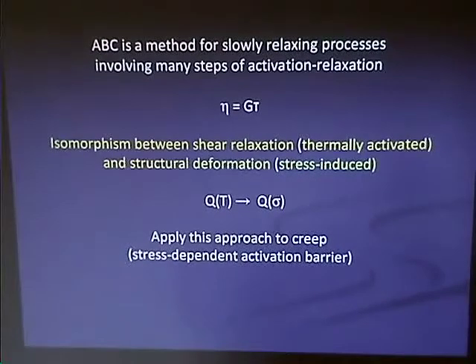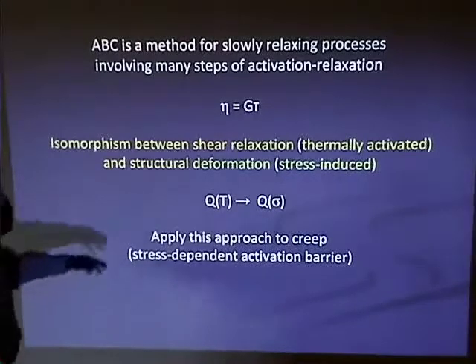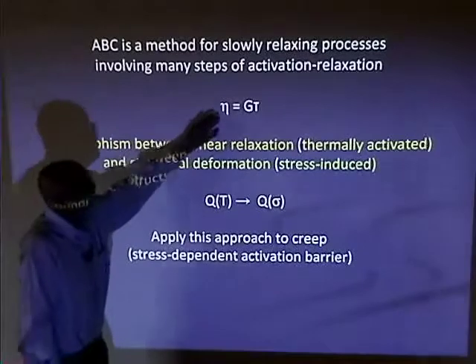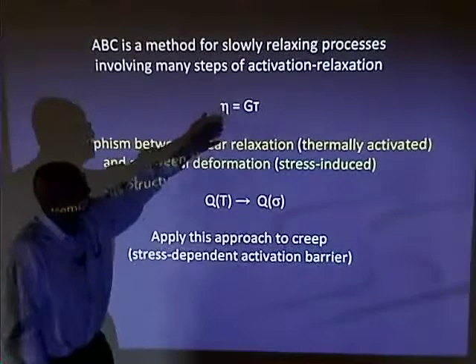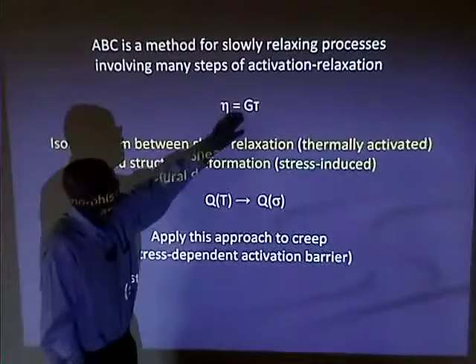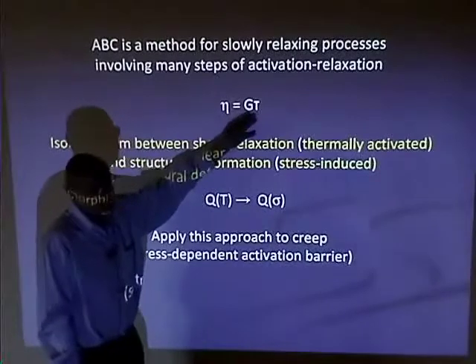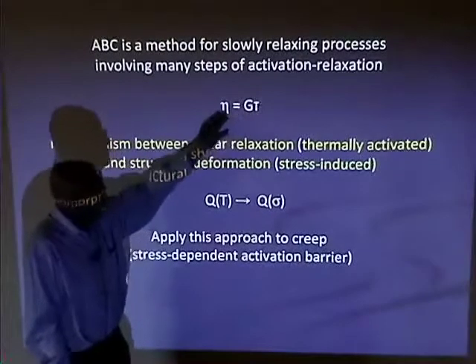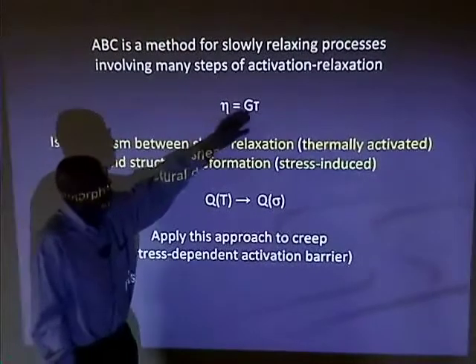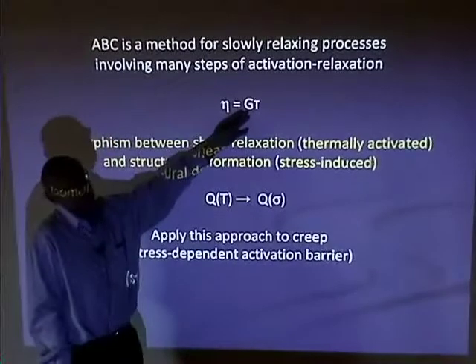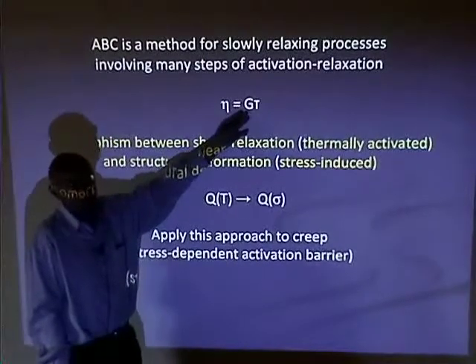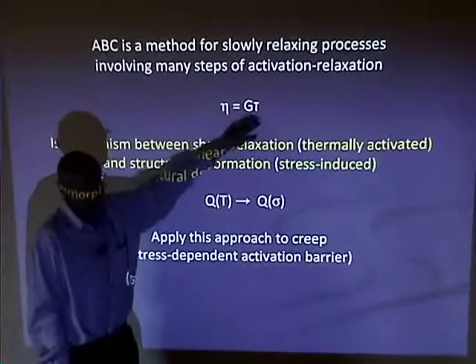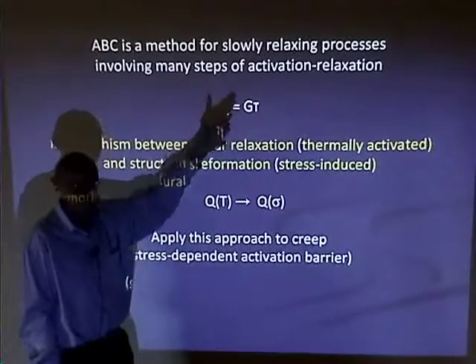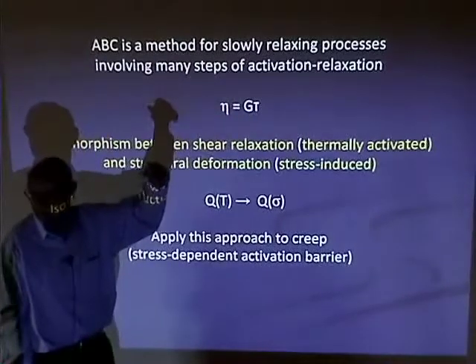The idea here is to notice that we've been talking about viscosity, but as mentioned yesterday, viscosity is nothing more than shear modulus times relaxation time. So we see 15 orders of magnitude in viscosity, but the modulus changes maybe one or two orders of magnitude at most. So it's all in the relaxation time. Basically what we're talking about is a slow relaxation time problem.